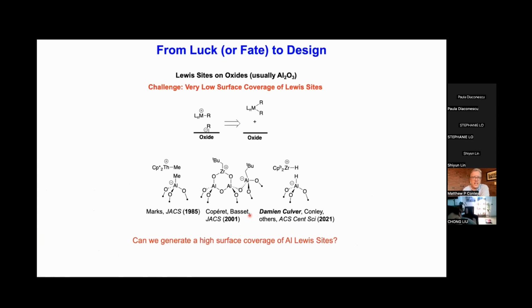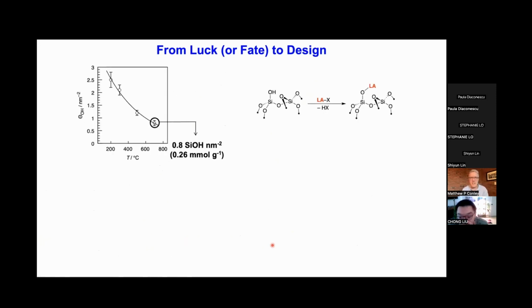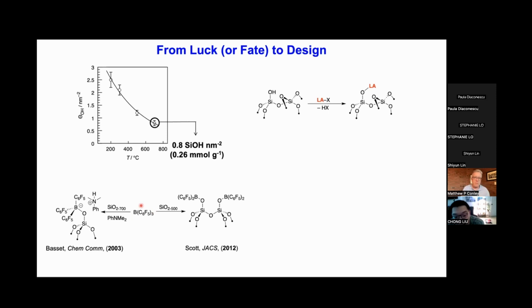So one question that kind of came out of this is that, okay, we have these examples here where you can ionize with a Lewis site, but these Lewis sites aren't normally present on very high surface coverages. They're difficult to characterize. Simply, can we generate a high surface coverage of aluminum Lewis acid sites? And this turns out to be a relative challenge in the area. So we go back to silica 700, sort of our baseline ligand in this area. And all we have to do is react some Lewis acid that can liberate HX to form a well-defined Lewis site. So the inorganic chemist's favorite Lewis acid is tris-pentafluorophenylborane.